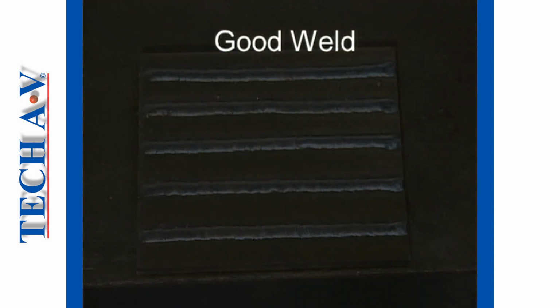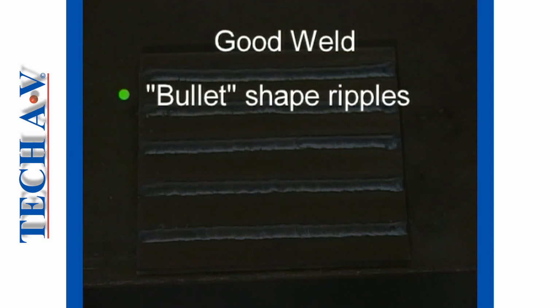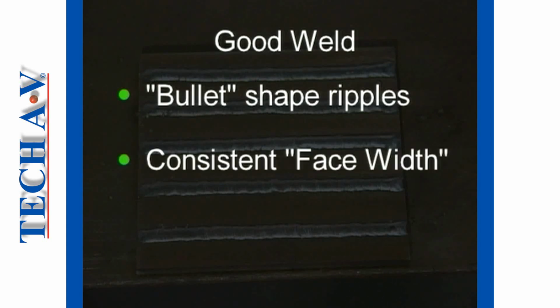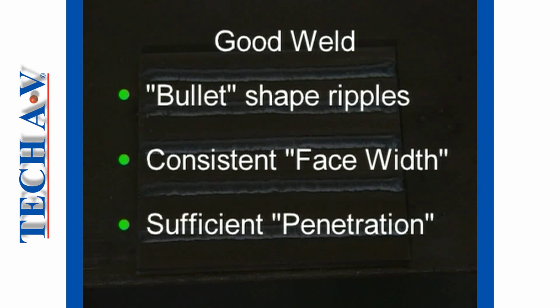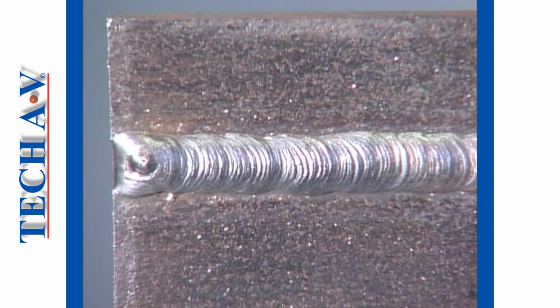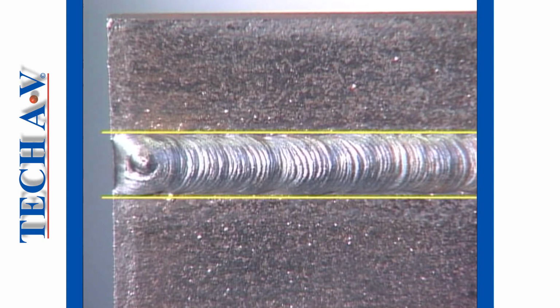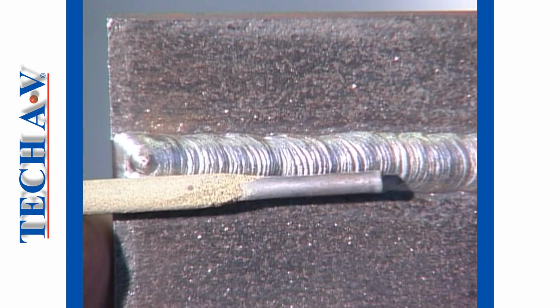A good weld has the following characteristics: bullet-shaped ripples spaced fairly evenly apart, a consistent face width of between 2 and 3 times the diameter of the electrode wire, and sufficient penetration into the base metal. If we look at the shape of the ripples on this weld, we see that they are bullet-shaped or C-shaped, and that they are fairly evenly spaced. Further, we can see that the bead width is consistent and approximately 3 wire diameters across.